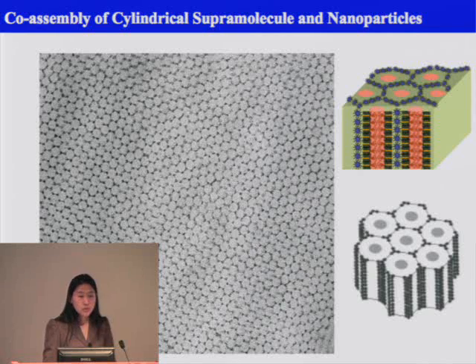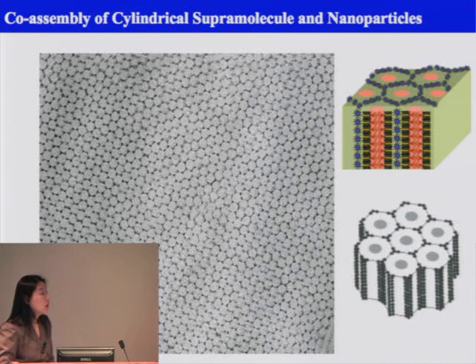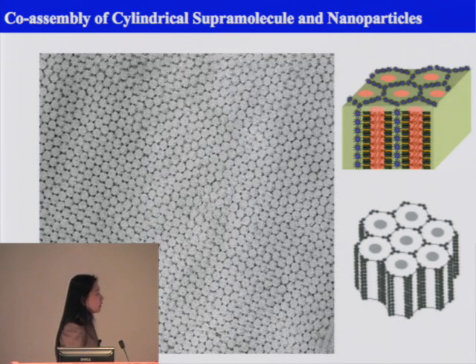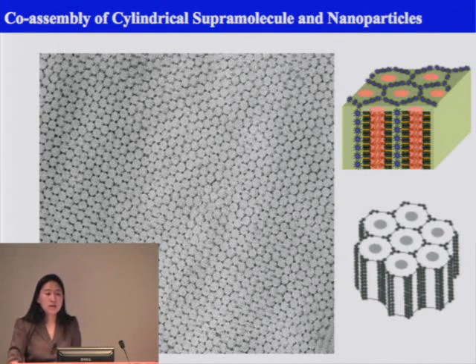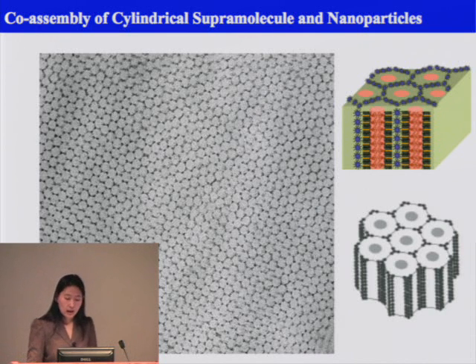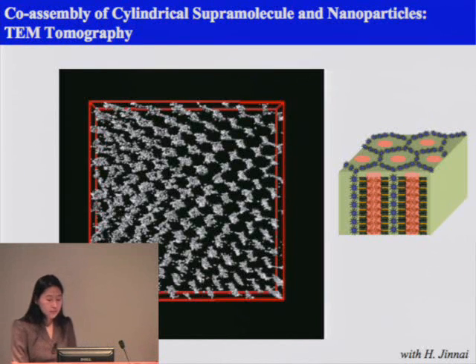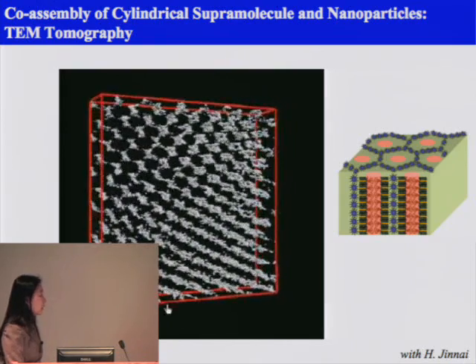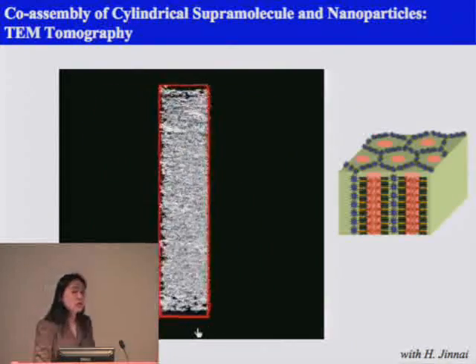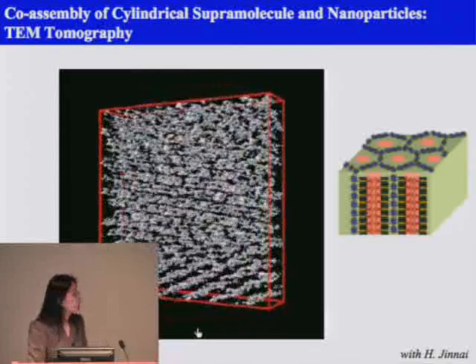One advantage we have with block copolymer is that you can easily control the morphology. By changing from a lamellae-forming polymer into a cylindrical microdomain-forming polymer, you can see the particles can easily form a hexagonal array, and there are a lot of unique optical properties that may arise from that. This is just to show you again the TEM tomography - you can see this beautiful honeycomb made of nanoparticles.